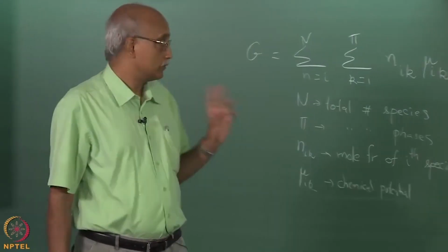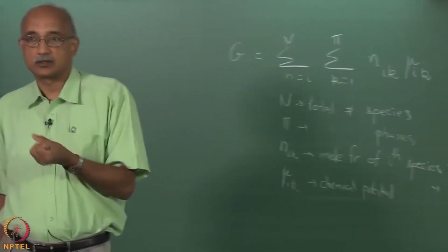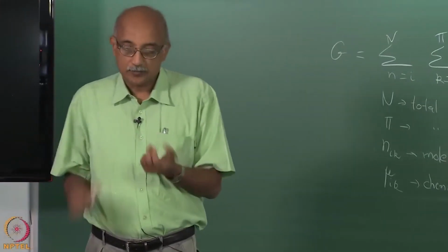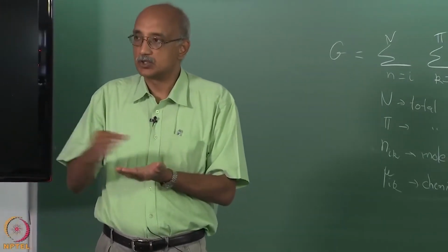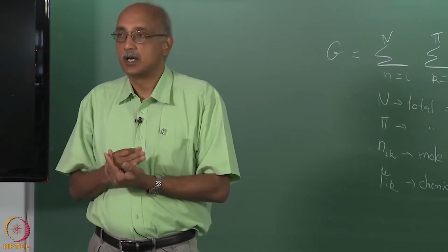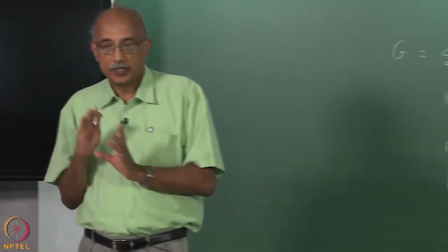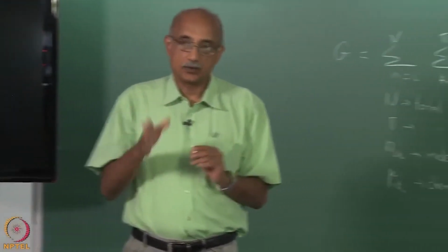One thing you have to be watchful about is that because the expression for free energy is quite complex, there are many local minima. So, you have to be able to differentiate between the local minima and the global minimum and home in on the global minimum. So, you need to choose numerical techniques that essentially allow you to do that.